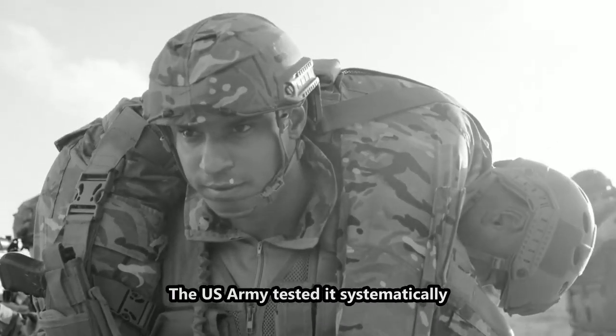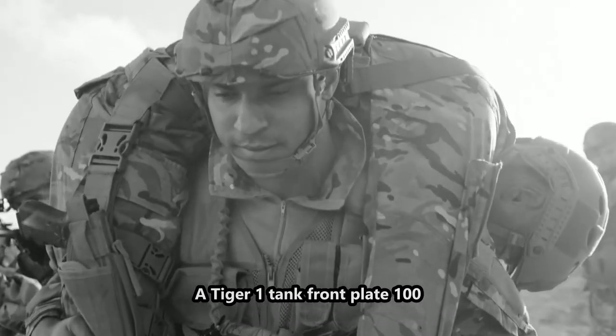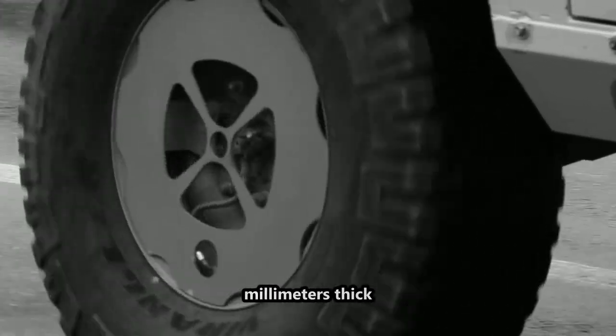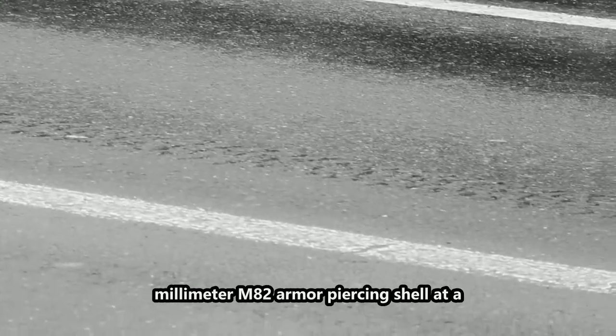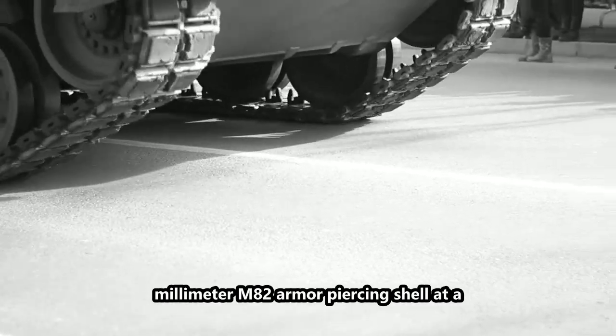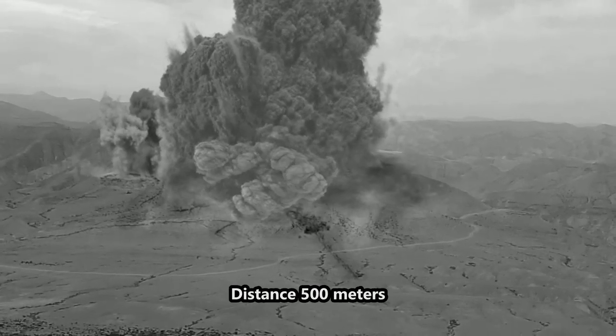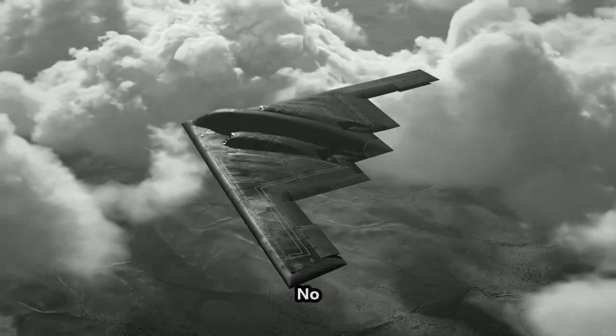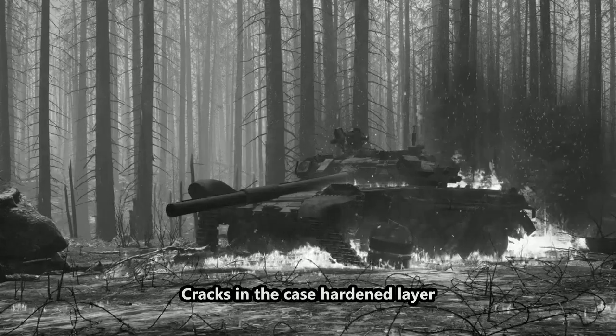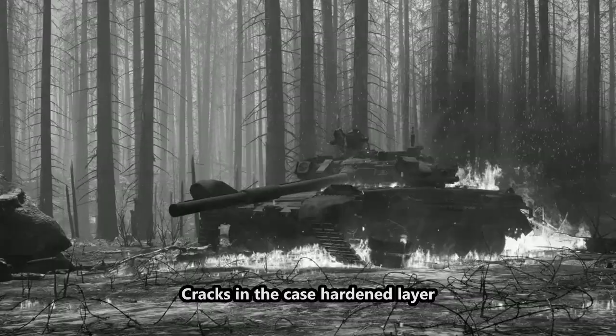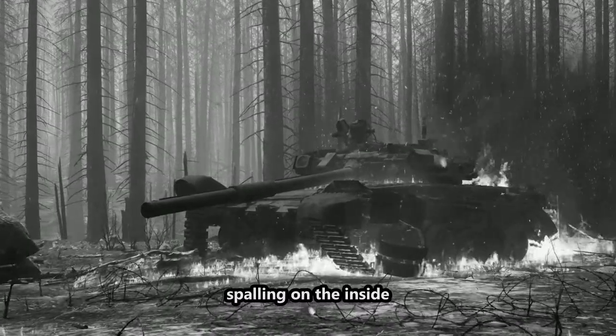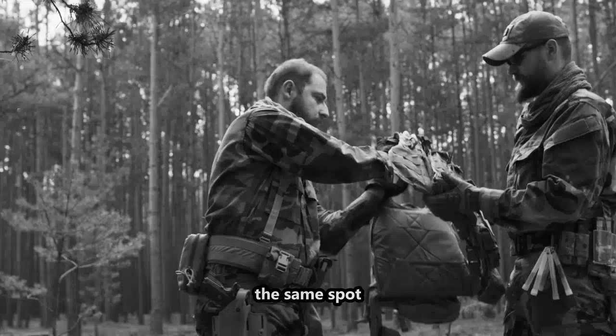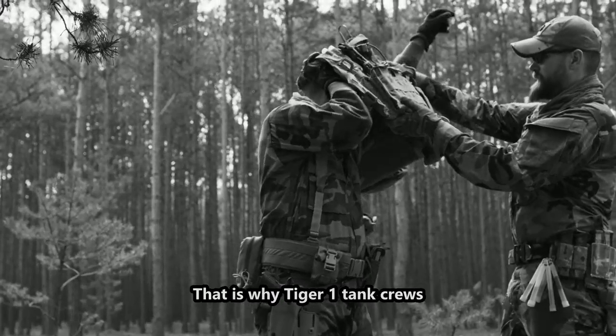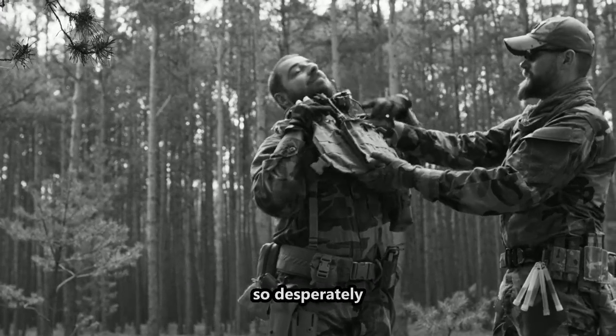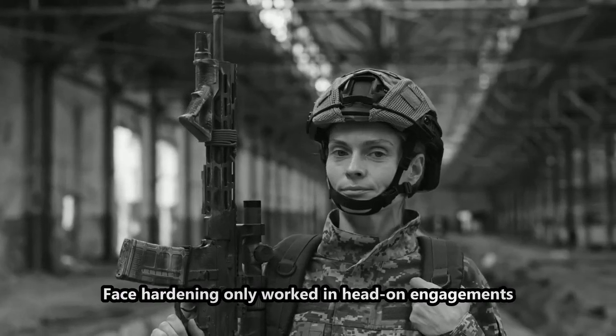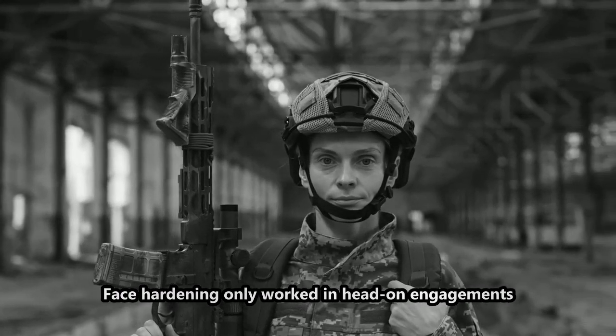The U.S. Army tested it systematically. A Tiger I tank front plate 100 millimeters thick, shot with a 90mm M82 armor-piercing shell at a 30-degree angle. Distance 500 meters. The result? No penetration, but massive surface damage. Cracks in the case-hardened layer, spalling on the inside. A second shot, the same spot, penetration achieved. That is why Tiger I tank crews so desperately avoided angled positions. Face hardening only worked in head-on engagements.